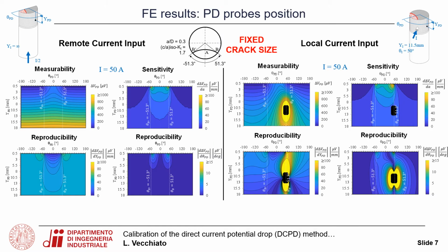For the sake of brevity, results of the finite element analysis have been reported just for the remote current input and for the local current input with the current probe at an angular position equal to 50 degrees for a fixed crack size. Results show the effect of the potential drop probes' position, as a function of their actual distance y_PD and their angular position theta_PD, on the measurability, sensitivity and reproducibility, which have been evaluated as the derivative of the potential drop value with respect to the actual position or the angular position of the potential drop probes.